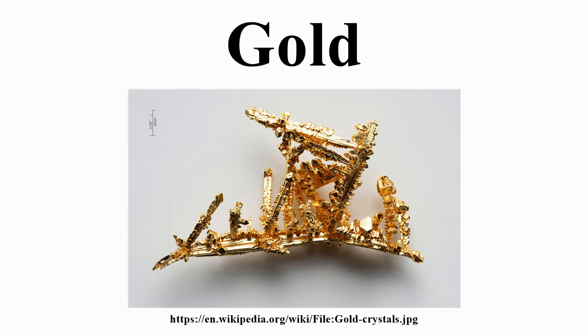This color is determined by the density of loosely bound electrons. Those electrons oscillate as a collective plasma medium described in terms of a quasi-particle called a plasmon. The frequency of these oscillations lies in the ultraviolet range for most metals, but it falls into the visible range for gold due to subtle relativistic effects that affect the orbitals around gold atoms. Similar effects impart a golden hue to metallic cesium.